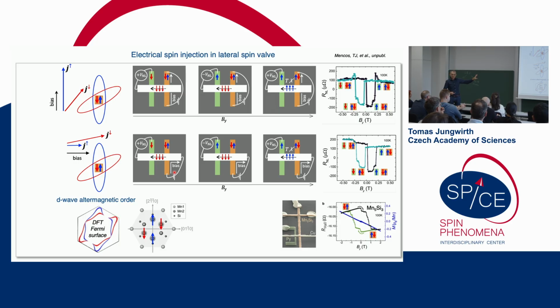And we don't actually have from neutrons in these thin films an unambiguous proof that we have this altermagnetic phase to start with in manganese-5 silicon-3. And it's notoriously difficult in thin films to get reliable neutron data to say that. So all the rest, this interpretation, was indirect, but the experimental facts that I mentioned are direct.